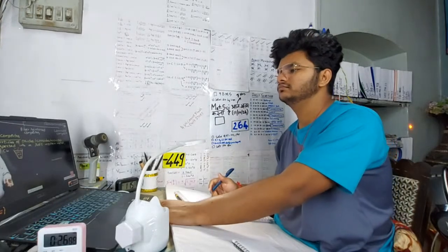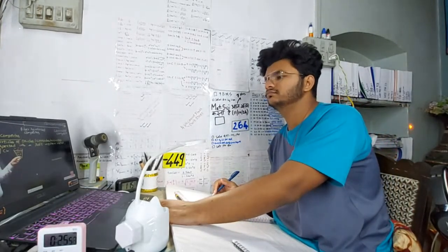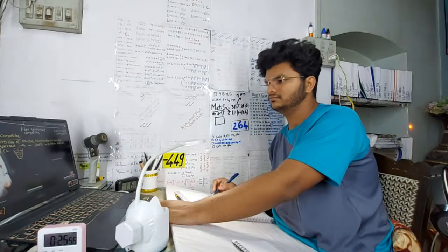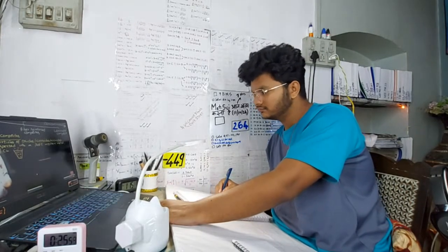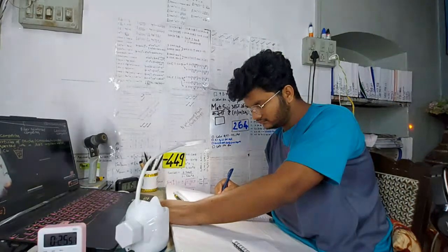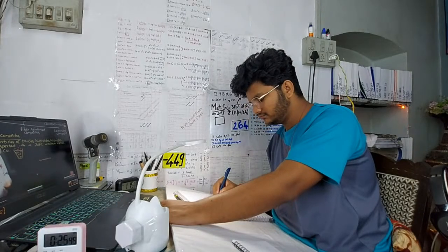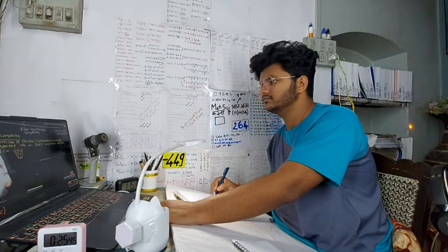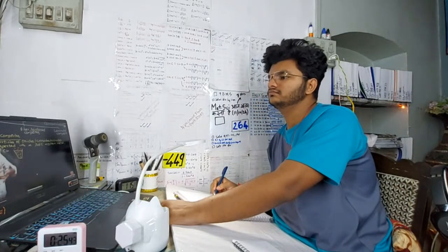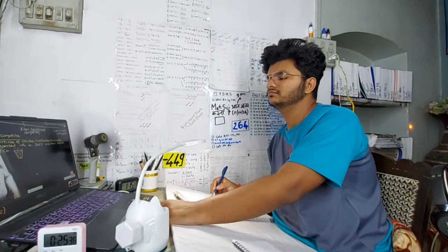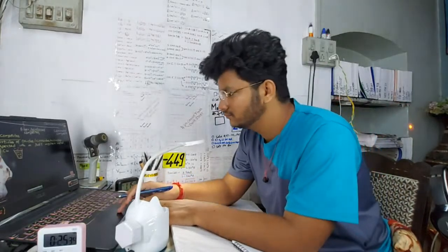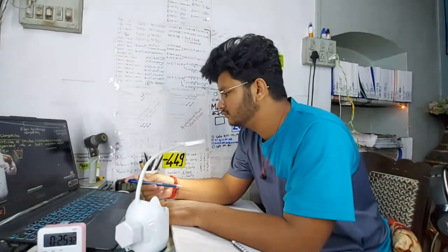That is the reason why when you mix the powder particles of oxides or carbides into this molten soft metal, they won't dissolve at all, because these powder particles have a very high melting point compared to aluminum or copper. So they don't dissolve, they don't typically react. Now, after thorough churning or stirring, the entire mixture can be poured into your mold, allowed to solidify.